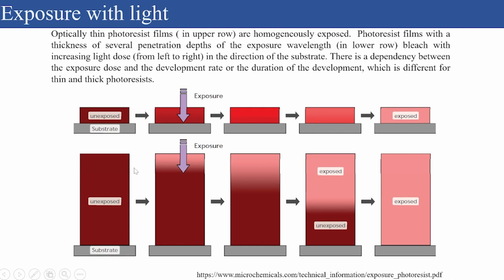But in case of the thick photoresist films, it is not homogeneously exposed, and we see that as we keep on exposing it with time, it increases layer by layer, and finally after sufficient time it is fully exposed. Hence it is very crucial to decide the dose as well as time. Now one interesting thing is that this dose and the exposure time are actually interchangeable. That means we can use a higher dose for a shorter time, or a lower dose for a longer time. This flexibility is also being used in our labs.